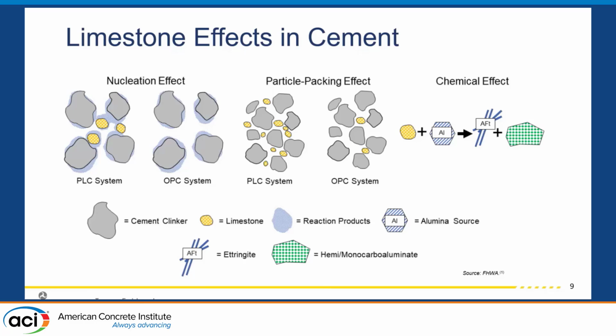So talking about PLC variability, what are limestone's effects in our cementitious matrix? You have a nucleation effect, so it acts as a seeding to allow more reaction products to start growing and developing. It has a particle packing effect. If you think about coarse aggregates in a tube, and there's all these air voids in between those coarse aggregates, if you pour sand into it, then you have less air voids between your coarse aggregates, right? It takes up all that space. Limestone acts the same way in a cementitious matrix. And then there's also the chemical effect that Dr. Burkan Isgor was talking about, where your limestone reacts with your alumina source to develop ettringite and hemi-monocarboaluminates.